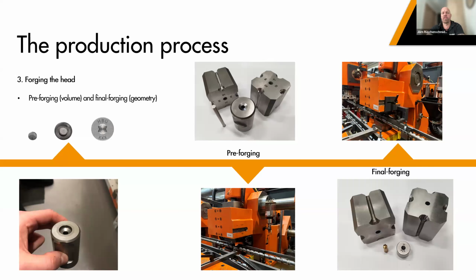So that means we first have the wires. The 3 dots you see on the top left are a top view of the screw. We first have the wire, then we bulge it out to a rough pre-forging geometry. And the second step then brings it into the final shape, including the drive as well as the imprint on the screw, which might be the type, the length, or even a brand logo.